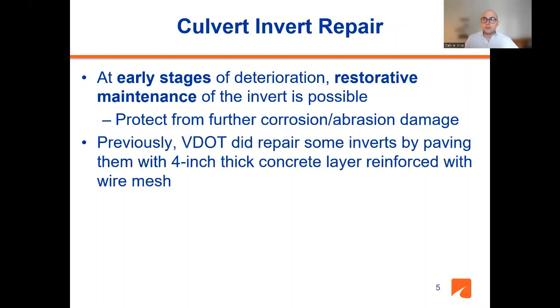At VDOT, some repairs were previously done, which consisted of paving that invert with a 4-inch thick layer of concrete that was reinforced with wire mesh. The 4-inch thickness and the wire mesh were used so that cracking could be prevented. Because of course, if you have an invert repair with a concrete material that cracks, water can continue to flow through those cracks and be in contact with the existing steel culvert and continue the rapid corrosion deterioration.